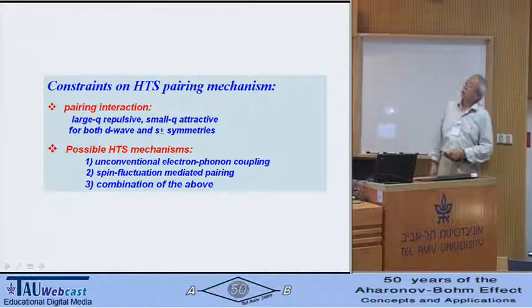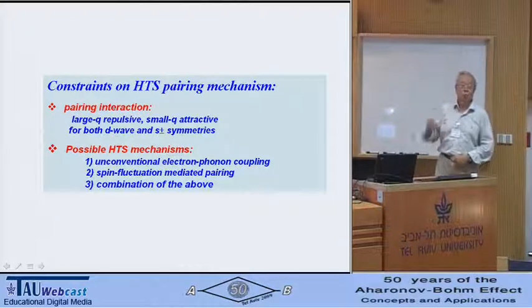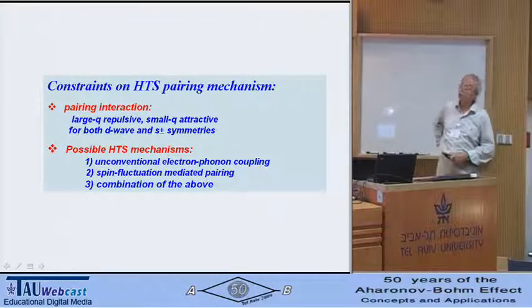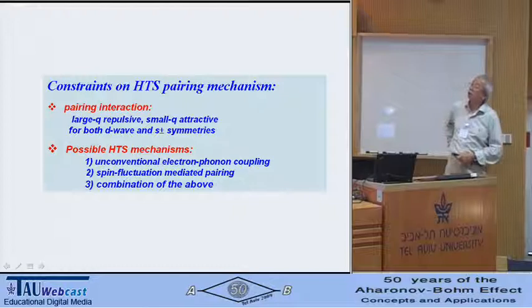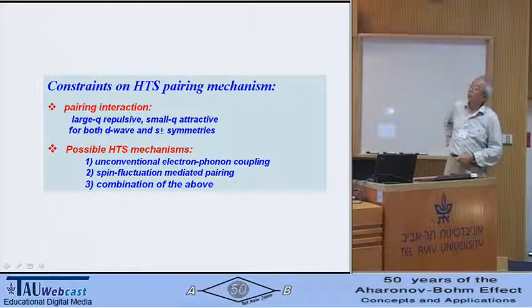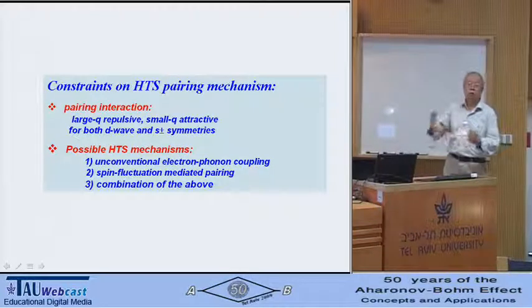The constraint on the high temperature superconductor pairing mechanism, this is what we really want to get a handle on. The basic message is to say that the pairing interaction has to be repulsive at large Q and attractive at small Q. This applies for both D wave and S plus minus symmetry. It turns out they give you the same requirement.